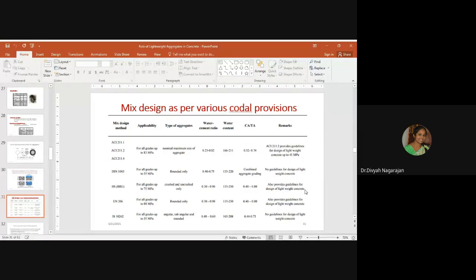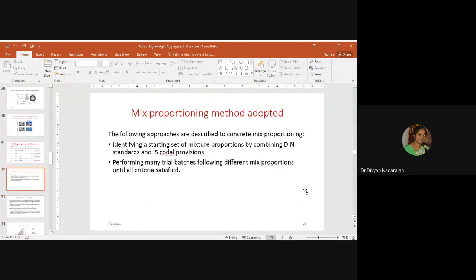The coarse aggregate or the total aggregate content varies between 0.4 to 0.75, and there are also no guidelines for design of lightweight aggregate concrete. So, although many literatures and international codes are available for mix designing, procedure and proportioning of this lightweight concrete, the lightweight concrete has to be mix proportioned by a lot of trial mixes. So the mix proportioning method that we have to adopt is from the trial mixes.